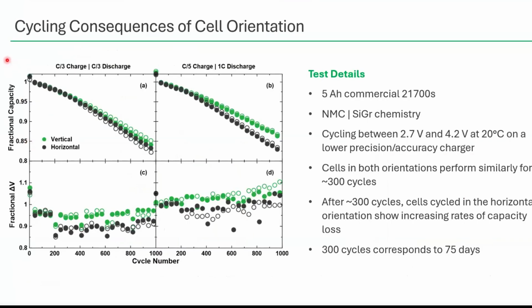So we did this experiment in-house on commercial 21700 cells. What we did is we tested them with different rates, C/3 symmetric charge discharge, or a C/5 1C charge discharge. What this is trying to do is keep the same total cycle time of approximately 6 hours, to control that side of the kinetics, and then change how much time the electrolyte has to really get back into the whole jelly roll, distribute, and have a nice, even concentration gradient within the cell.